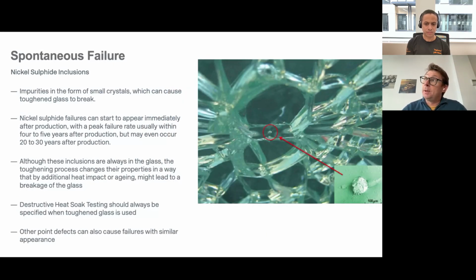And the tempered glass might not just be breaking from a fracture or an impact. Nickel sulfide inclusions are also present, and about 20 or 25 years ago this was much more common, as the level of impurities in the glass was higher. The processors, or the flat glass manufacturers, have gone to great lengths to reduce these nickel sulfide inclusions, and the possibility of them has dropped. Nevertheless, not all manufacturers are the same, and they're still present in glass in a quantity, so failures are still occurring, and we must be mindful of this, in that a glass does not sit on its own for an unintended period of time. There is also always a possibility that that glass breaks.